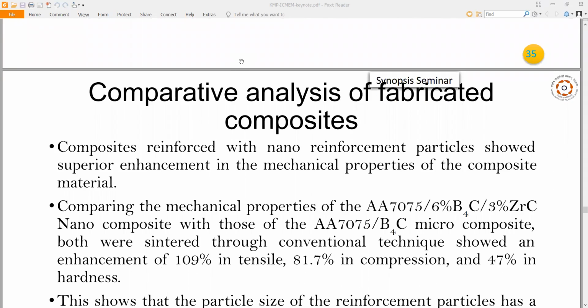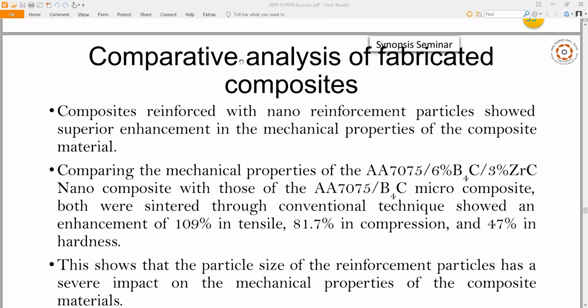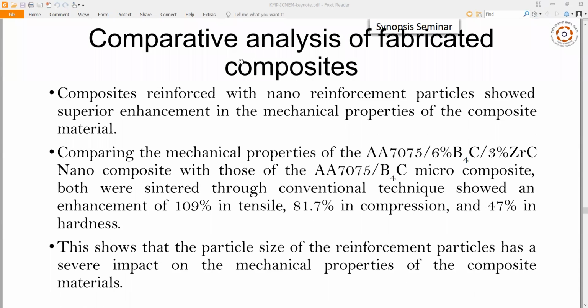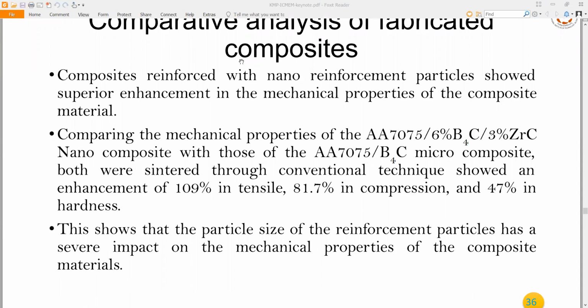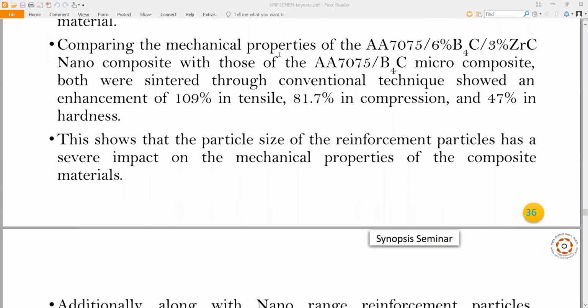Then this is about comparative analysis of fabricated composites. Composites reinforced with nano-reinforcement particles showed superior enhancement in the mechanical properties of the composite material. Comparing the mechanical properties of the AA7075, 6% B4C, 3% ZrC nanocomposite with those of the AA7075 B4C microcomposite, both sintered through conventional technique, showed an enhancement of 109% in tensile, 81.7% in compression, and 47% in hardness. This showed that the particle size of the reinforcement particle has a severe impact on the mechanical properties of the composite materials.